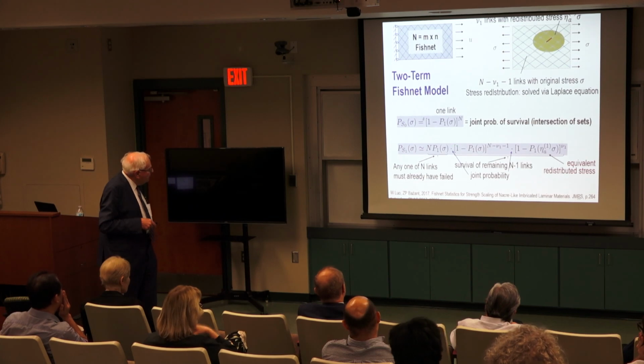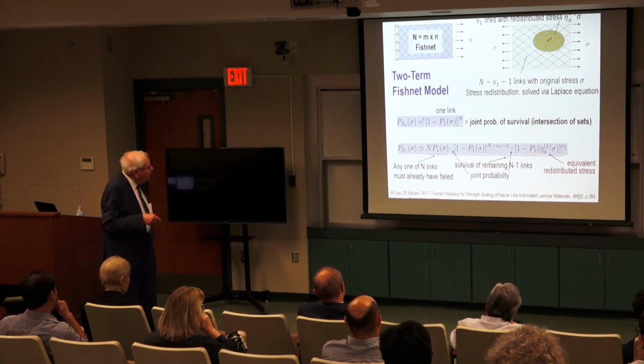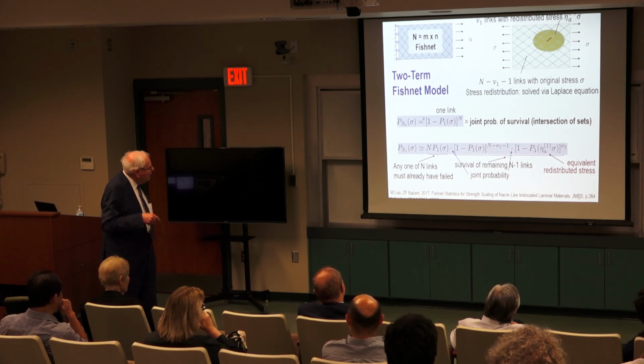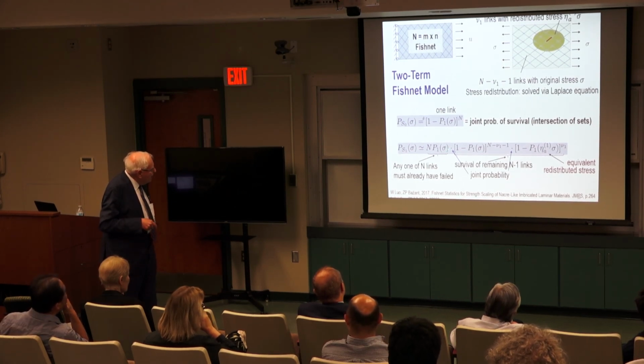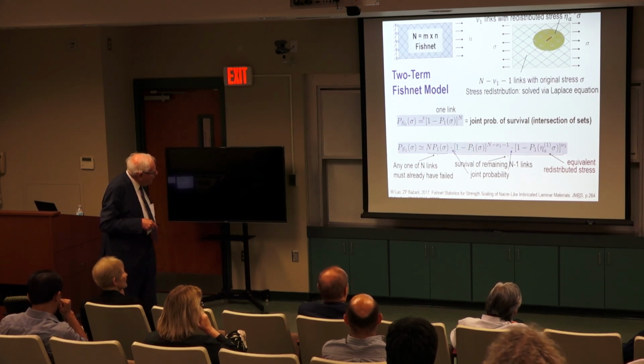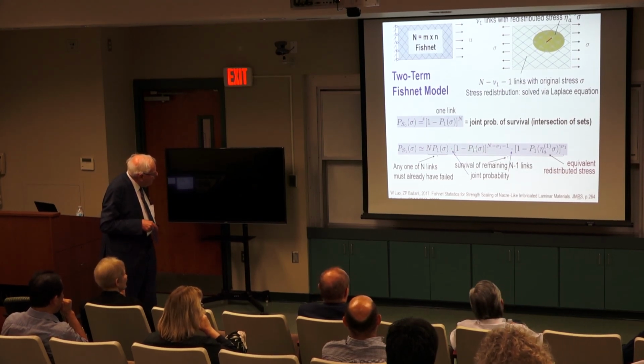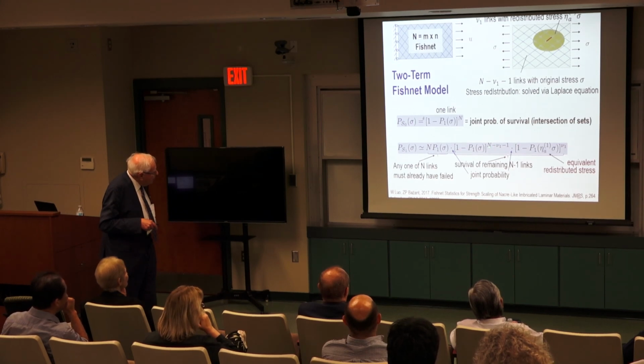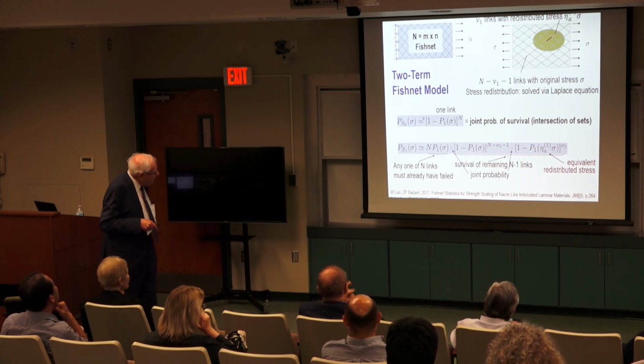Now, for the second term, we can argue similarly. It can start at any of n points. There are n elements here in the fishnet, and that must happen simultaneously with survival of the rest. So the survival probability is this difference, 1 minus the failure probability, and it must occur jointly. So n, but you must distinguish elements which are redistributed from those which are not.